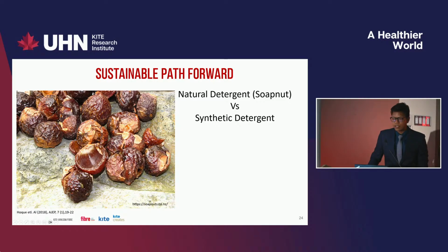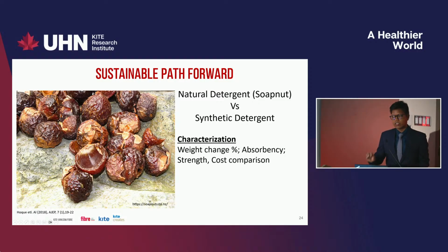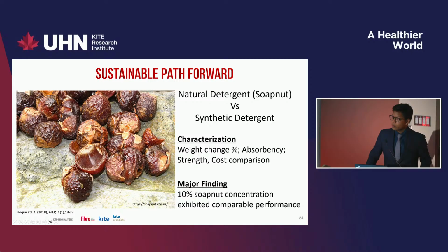Maybe some of you know soap nut. Soap nut is a naturally abundant material. It has some surfactant properties. So we wanted to see if soap nut can be an alternative to synthetic surfactant. So we tried different concentrations of soap nut: 1, 3, 5, and up to 10%. And we characterized the performance by weight changes and by absorbency, because if I consider the next step as dyeing, absorbency is important. We characterized the strength of the material after this processing, and we also tried to compare the cost consumption. So the major finding is that with the 10% soap nut concentration, we found comparable performance. The performance was comparable in all of the categories I mentioned above.